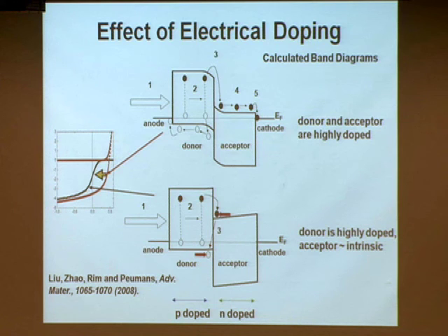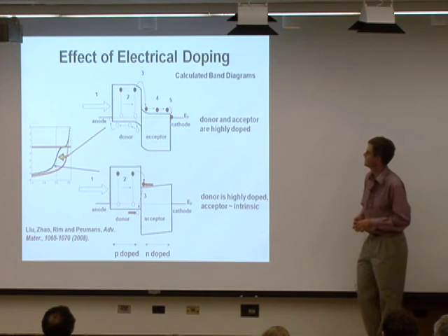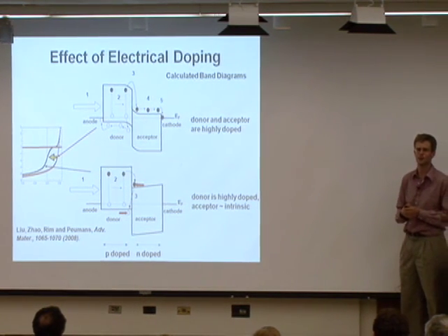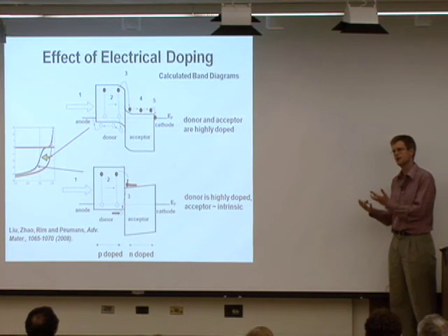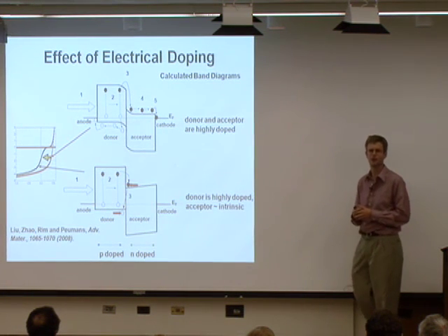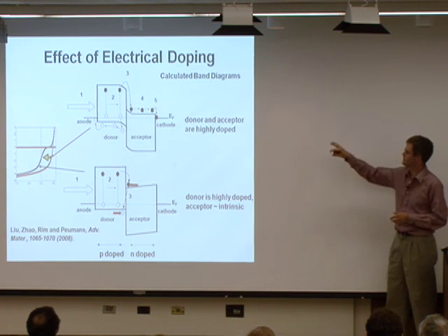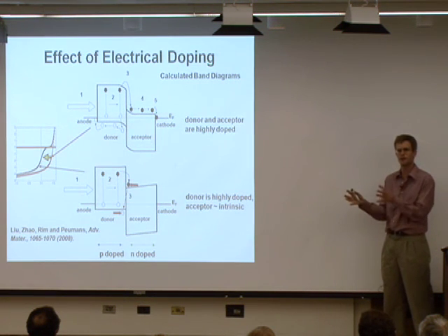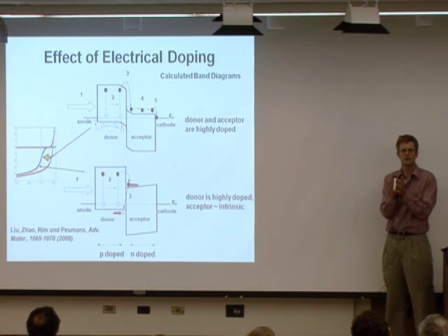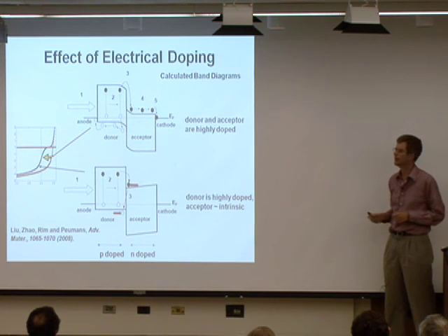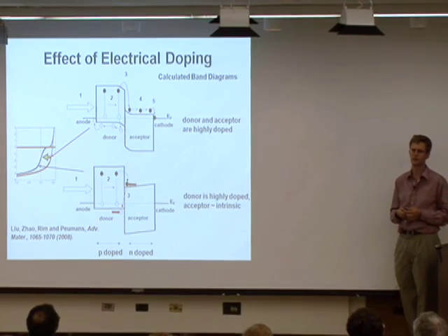When the exciton splits, you have an electron right here and a hole right there, and you want to pull them apart, and so that's where you need an intense electric field. So it's actually best to dope the materials and split your excitons. And so perhaps I should not have said that the dopants were undesirable. In fact, it turned out that those impurities were a good thing. And now that they understand this, they can purify the materials and then put in a dopant at a highly controlled level to optimize the performance of these solar cells.